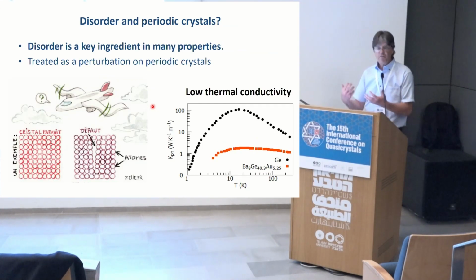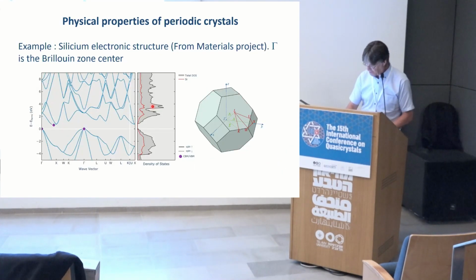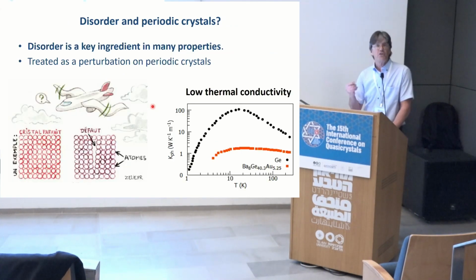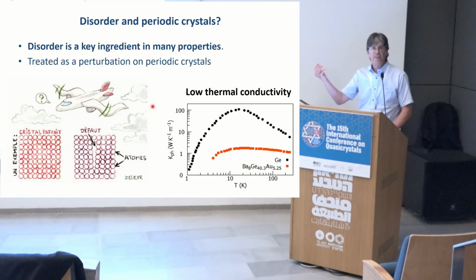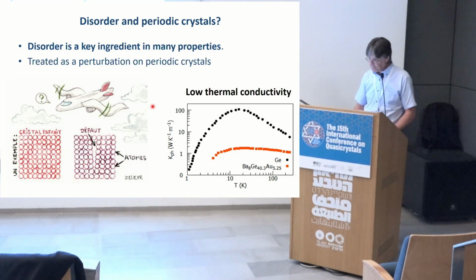But if we have disorder, so just to make things clear, again, periodicity is a key ingredient here. If we have disorder, most of the time disorder is taken as a perturbation on this periodic potential. That's the case, for instance, in the thermal conductivity. If you introduce disorder, this is pure germanium. If you have a complex structure with disorder, then the thermal conductivity drops down, and this is due to the disorder.